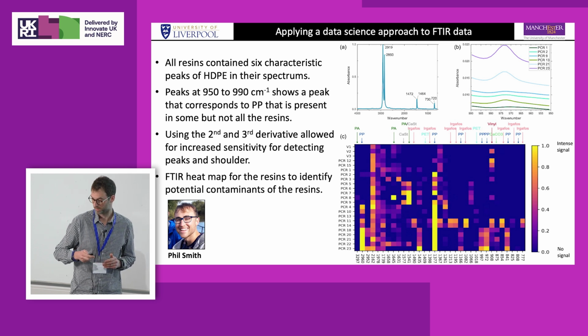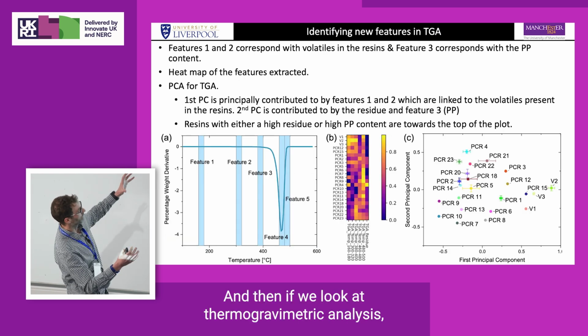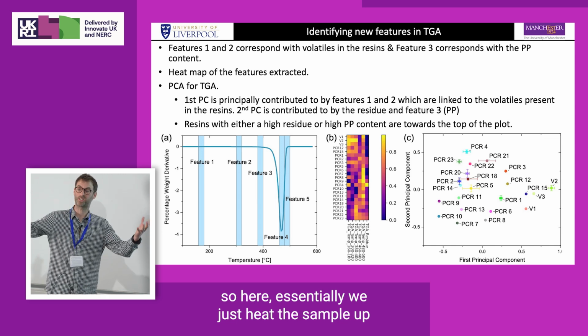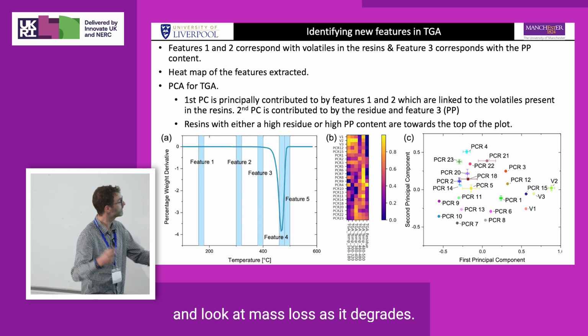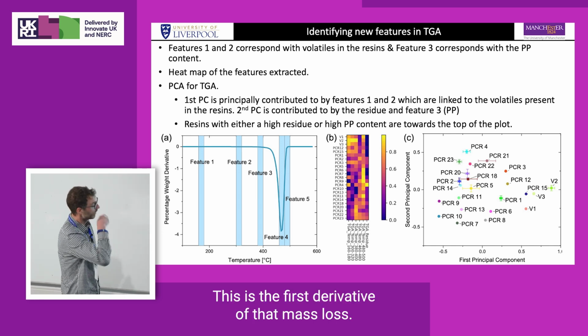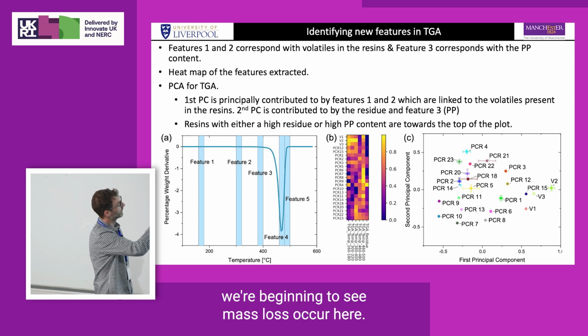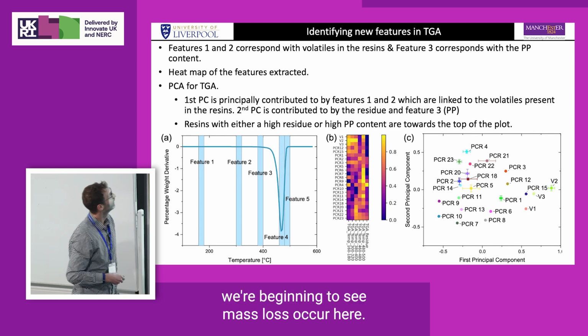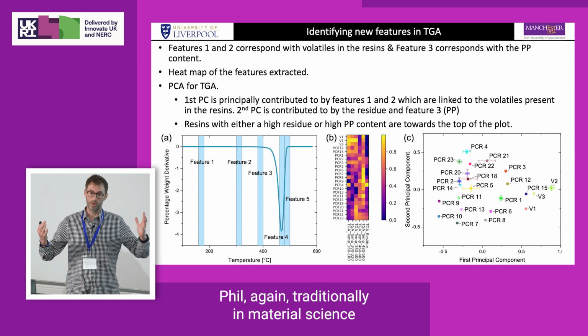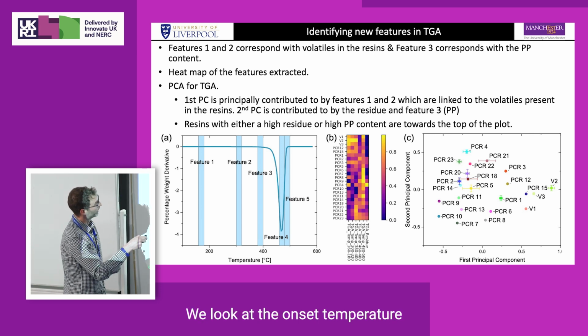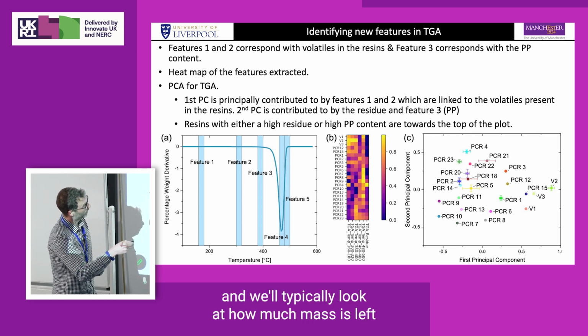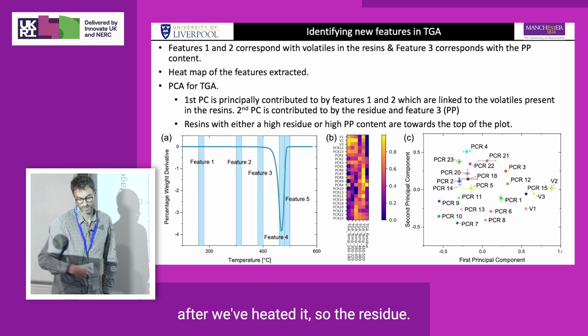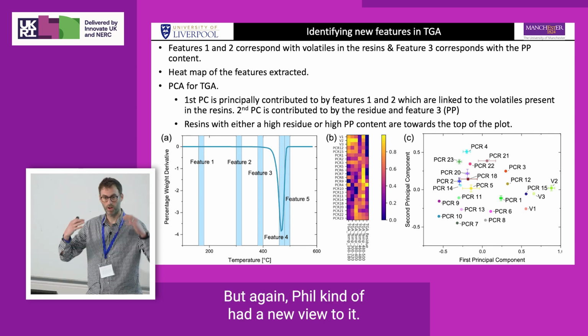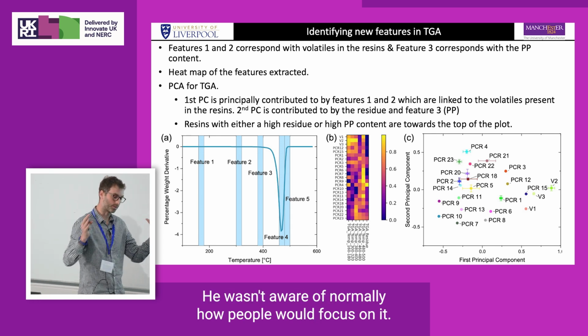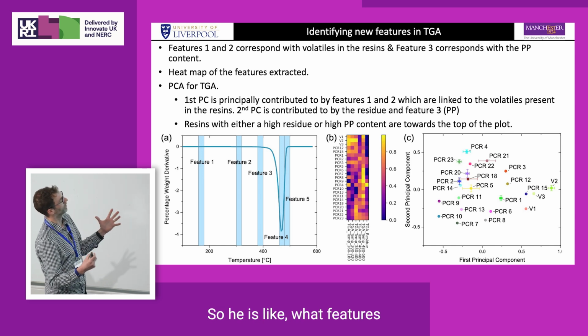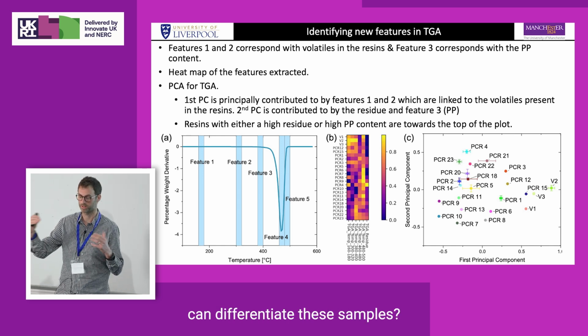Okay. And then if we look at thermogravimetric analysis, here we essentially just heat a sample up and look at mass loss as it degrades. This is the first derivative of that mass loss. As we heat it up, we begin to see mass loss occur here. Traditionally in material science, we just look at a couple of things. We look at the onset temperature, and we'll typically look at how much mass is left after we've heated it, so the residue. But again, Phil had a new view to it. He wasn't aware of how people would normally focus on it, so he asked, what features can differentiate these samples?